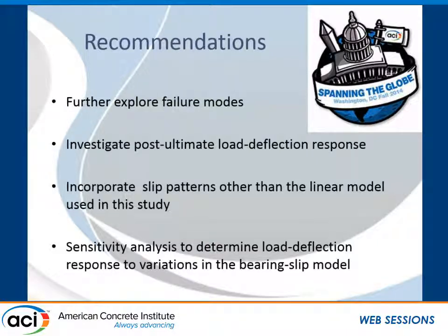We would also like to explore post-ultimate load deflection behavior and especially work on adapting the method for use with different slippage span relationships in cases for which the distribution of bending moment is different than what we had with our beam tests. The proposed model and methodology uses a bearing-slip relationship that is specific to the chosen fastener type, size, and manufacturer. And in order to predict beam behavior with a different fastener, this then requires a bearing-slip relationship specific to that fastener to be developed and incorporated into the analytical model.